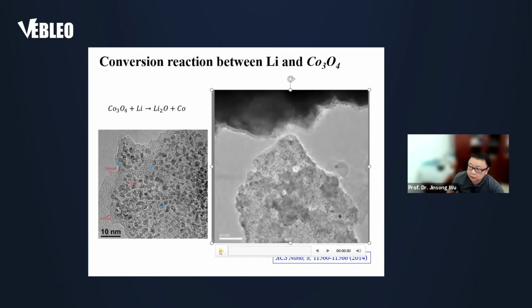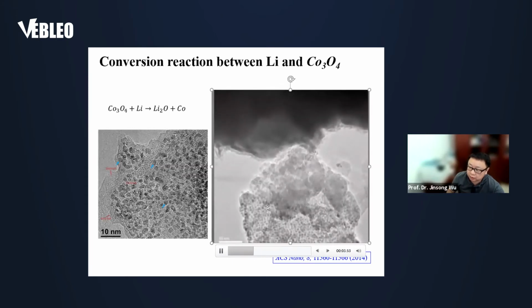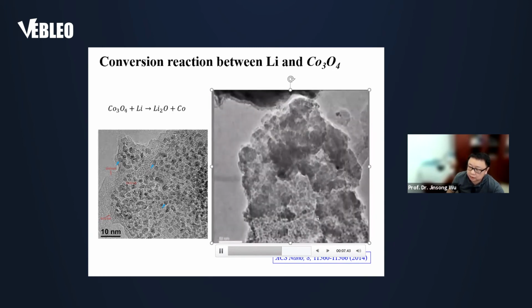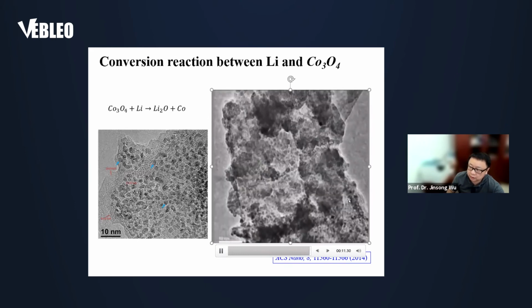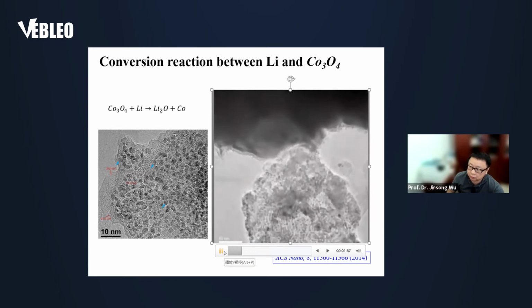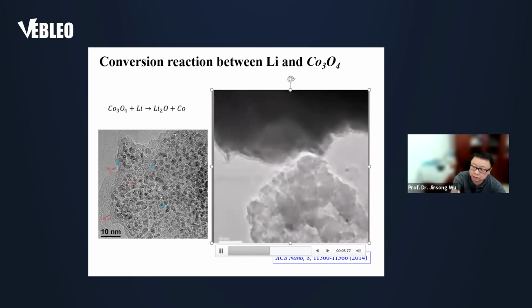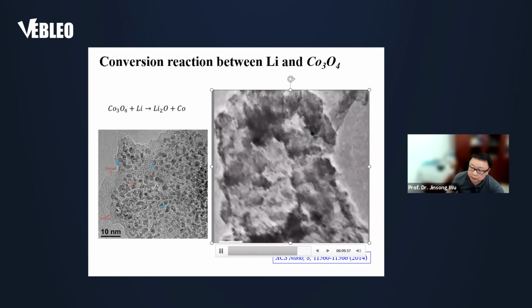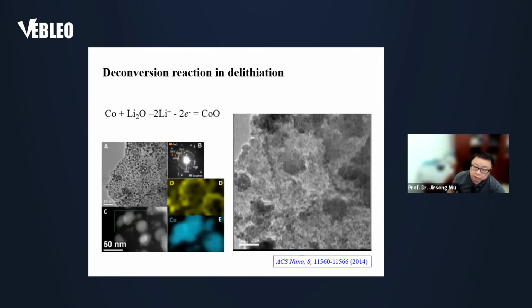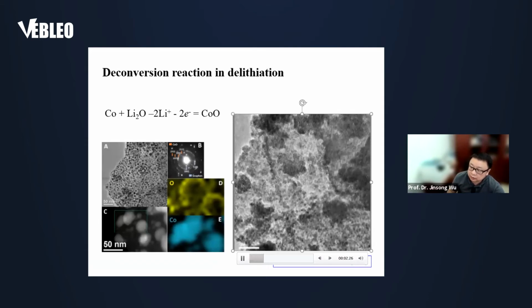So in this video, once we make a contact, you see the reaction front moved quickly toward this side. And this video shows the products of the reaction. Especially by using high resolution electron microscopy, we can identify that the small particles are cobalt metal embedded inside the lithium oxide matrix. And it can thus be determined that this is a so-called conversion reaction: the cobalt oxide reacted with lithium, and the reaction products are lithium oxide and cobalt metal.